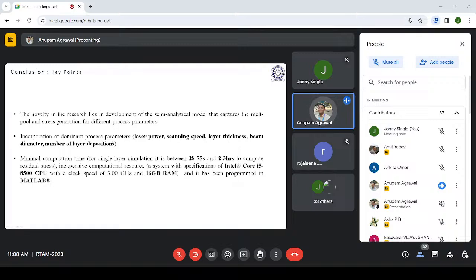These key points are not the overall conclusion. There is something still left. This particular part of this work found that the semi analytical model gives us very good results in terms of melt pool dimension and stress generation for different sets of process parameters like laser power, scanning speed, layer thickness, beam diameter, we varied beam diameter also but have not shown those results, and number of layer deposition. For a different number of layers it definitely gives us very good results, and it is quite fast also. However, let's see,